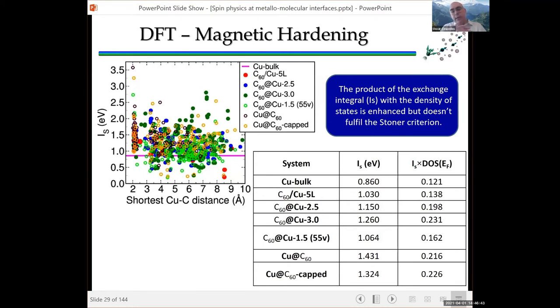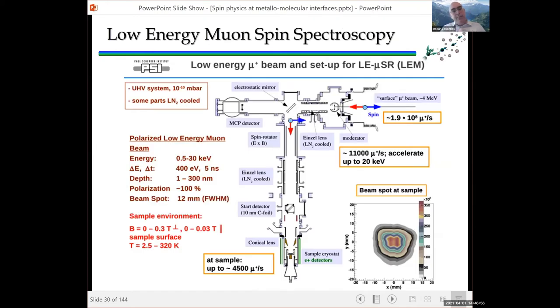Right, so very quickly, I'm going to explain a little bit about low energy muon spin spectroscopy, because it's perhaps a technique that not many people use. It's only done really in PSI, Paul Scherrer Institute in Switzerland. J-PARC in Japan also does it sometimes, but it's not so stable, not so high currents, and only sometimes. So here what we have is conventional muon spin spectroscopy, which is more extended. But what they do is they moderate the energy of the muons using an argon solid cryogenic filter. So they slow down these muons from energies of mega electron volts to almost zero. And then they re-accelerate these muons to energies of the order of kilo electron volts.